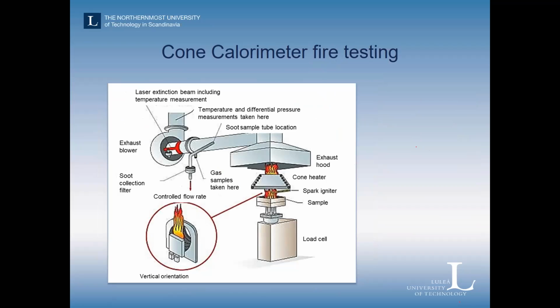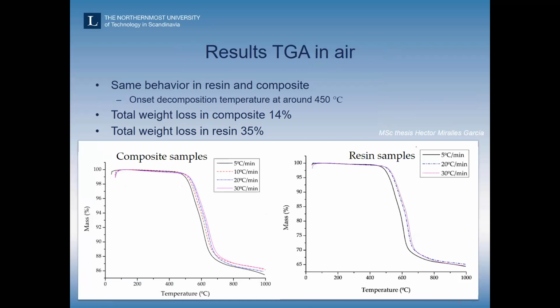And in order to save some, so we can go back, by the way, here. So the first way of looking into the thermostability of composites, the obvious way, is to look at the TGA, thermogravimetric analysis, and look for degradation and mass losses when running temperature scans. And what we've done here is to analyze composite samples and resin samples. And these are the typical curves obtained from TGA measurements at different rates.